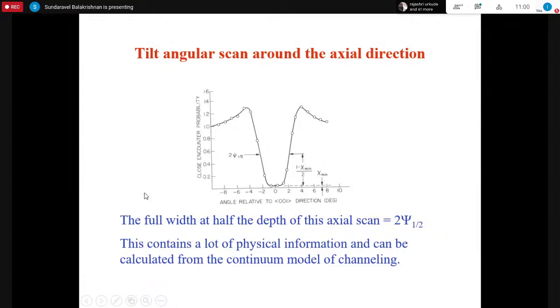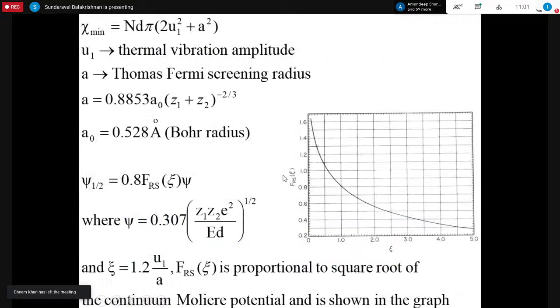And as such, when you align the beam exactly on the crystalline direction, I told you there will be minimum backscattering, or the minimum value, chi minimum. And when you tilt the sample out of the axis, this yield will keep increasing. When you go something like 2 degrees off, you will get a higher value, close to the normal RBS yield value. Whatever this width is, it is 2 times psi half, and psi half is connected with that critical angle of channeling.